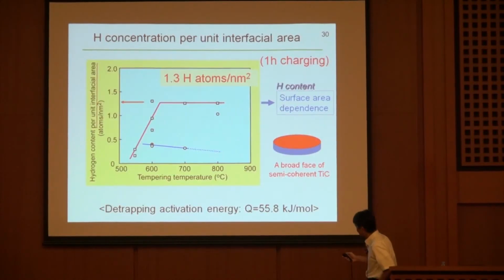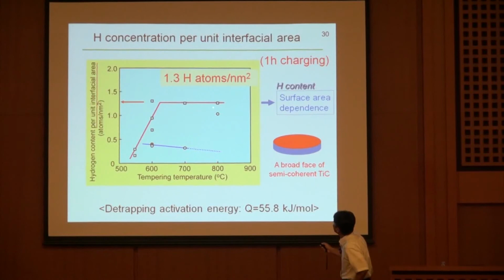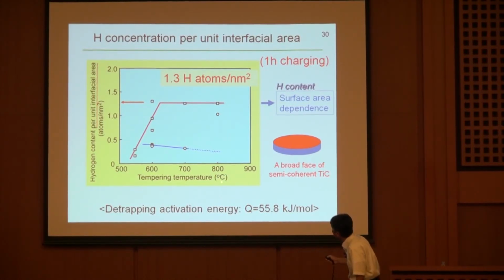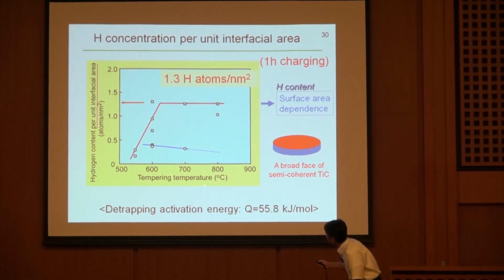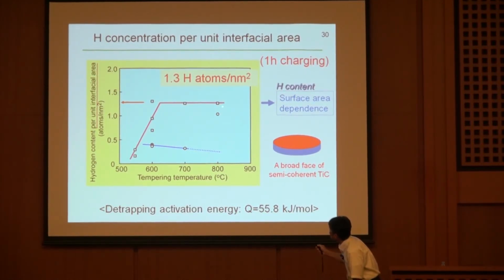However, if you look at here, this hydrogen concentration per unit area isn't changed like this, constant. This is because the coarsening of carbide occurs with increasing tempering temperature. But I was so surprised here. So this is a constant.